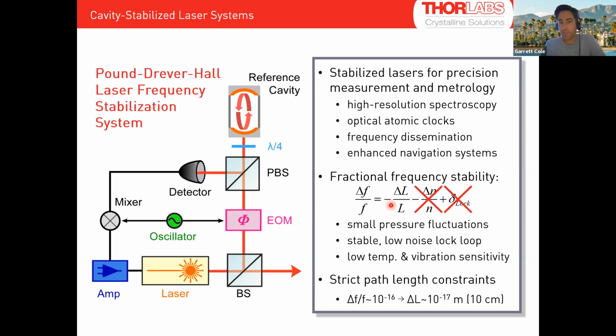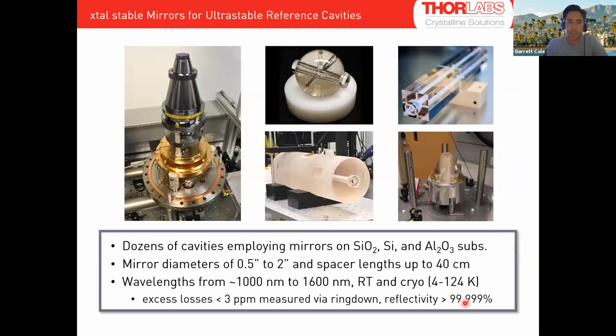To show why you see Brownian noise, these state-of-the-art laser systems show a delta F over F, or frequency instability, at the 1 part in 10 to the 16 level. So this is sub-hertz, when you have many terahertz of frequency. So you are looking at a length fluctuation on the order of 10 to the minus 17 meters in that system, right? That's deeply sub-proton radius. So you're looking at tiny fluctuations. That's why you see stuff like Brownian noise, in this case for a 10 centimeter long cavity.